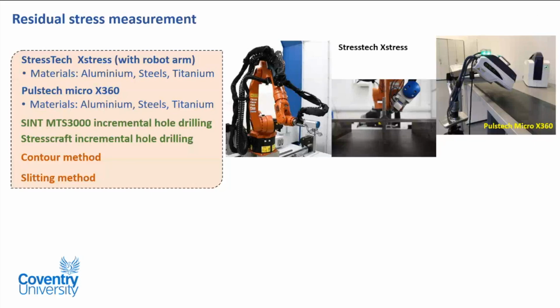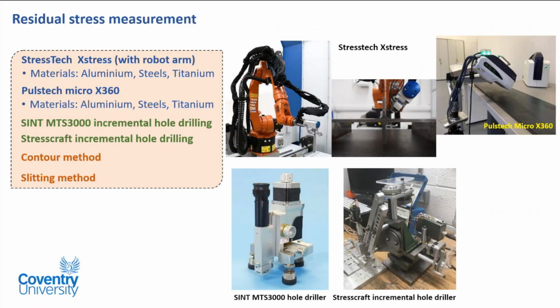So just a few slides to show the equipment. We feel we are quite unique. We do residual stress measurement, and the first picture you see is by diffraction mechanism. So it's the laboratory-based X-ray diffractometer. But the thing I want to show is they all have a robotic arm, so it can measure 3D shape. The picture in the middle is actually a cruciform weld from TWI, and we were detecting residual stress. Then there's also a complementary tool called incremental hole drilling. By drilling tiny small holes, it's not destructive, but it can verify the XRD.